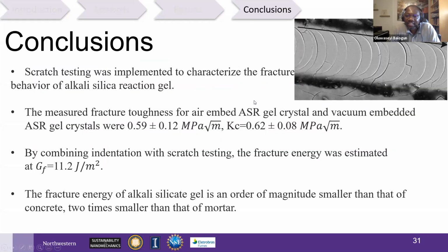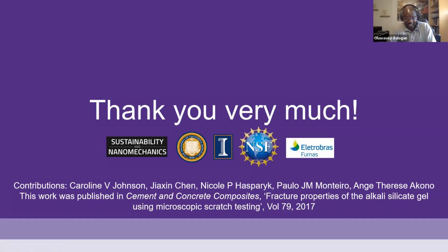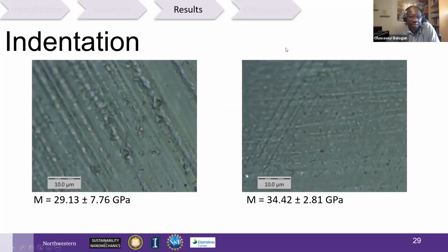Okay, I can take a shot at it. If you go to slide 29, I was curious about the dependence of your indentation modulus on the fact that you're in air or in vacuum. If we think about the modulus of the material as being intimately connected to the interatomic bond stiffness, I'm not sure exactly why you see a difference between the moduli of the two materials.